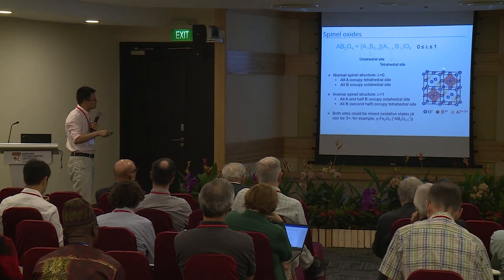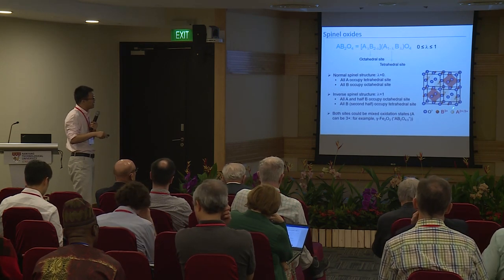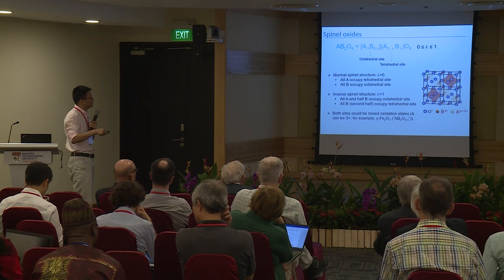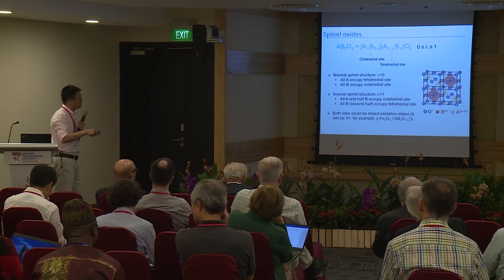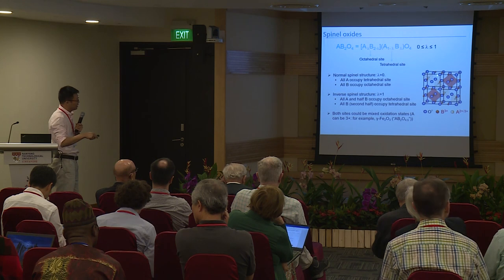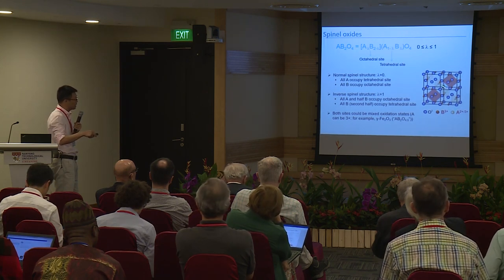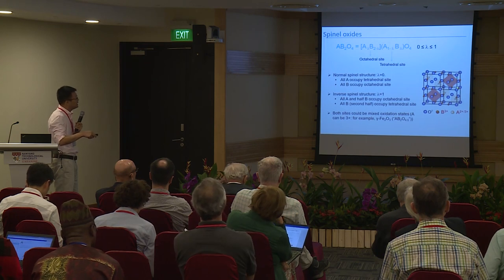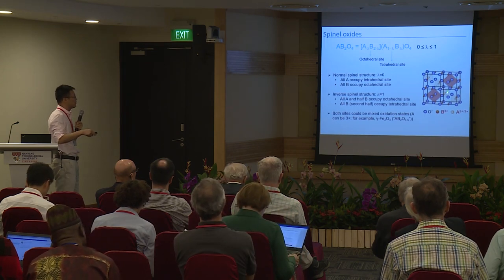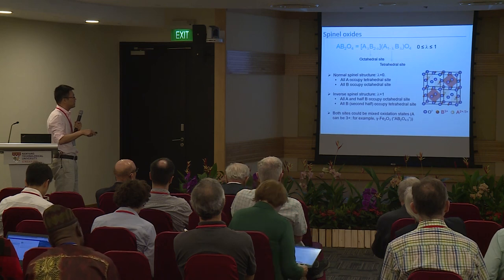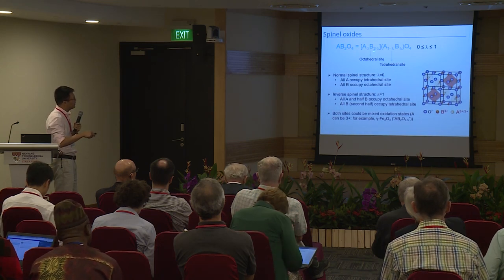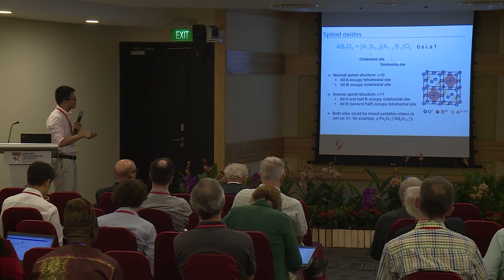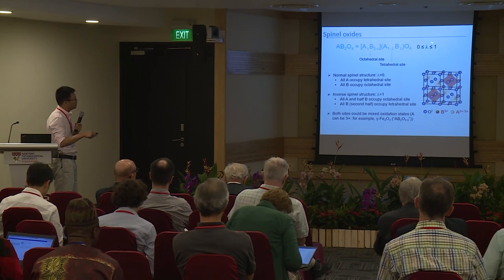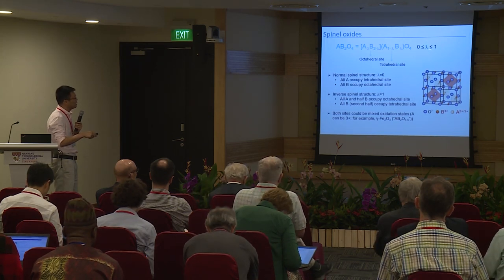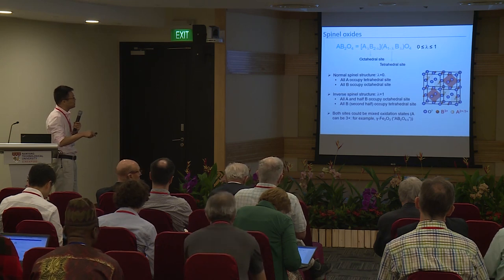So this is a cubic structure of spinel. You can see that oxygen forms some geometry hosts. You can see the tetrahedral host and the octahedral host. We can call these geometry sites. Now, your cations A and B actually can occupy both octahedral and tetrahedral sites. So that means some A and B are in octahedral sites, some of them in the tetrahedral sites. That introduces one important parameter, which is lambda. We call it the inversion degree. Lambda is between 0 and 1.